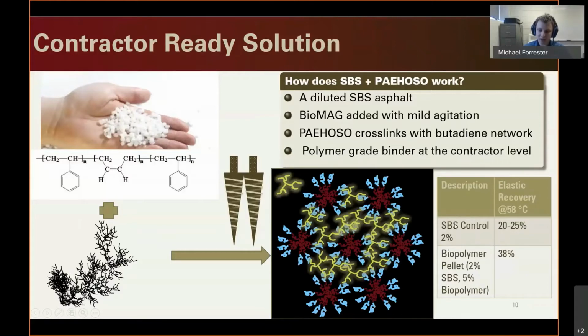Typically, if you take SBS and asphalt at the dosage rates of additives that we have, you can get to about a 20 to 25% elastic recovery. With the biopolymer pellet system, you can actually get up to about a 38% elastic recovery. This isn't perfect. We've done better with our pure Biomag system that's blended in the high shear facility.